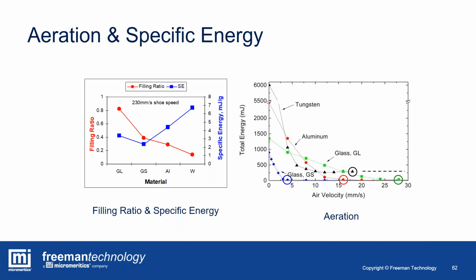What's a bit strange here is that the best flowability material is the small glass beads. It's got the lowest specific energy, so the lowest mechanical locking. It fluidizes, and yet it only fills to 40%. Whereas the large glass beads, it's not bad in terms of its specific energy. It's a value of about 3.5, which is moderate, but it's higher value, of course, than the smaller beads, and yet it fills to 82%. And the question is, why is that? You might expect, for example, this interlocking parameter to be a bit lower to support the fact that the material behaved well in the process.